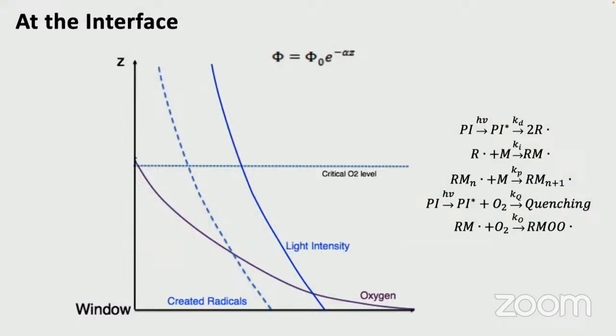So if you look at what happens, light comes in. This is a UV curable resin with a photoinitiator. Light comes in, it decomposes the photoinitiator, and generates a radical pair. That radical pair can do one of two things. If there's oxygen present, the reaction with oxygen is far greater than it is for kicking off a polymerization. So there's a competition between inhibition with oxygen and initiation of a polymerization.